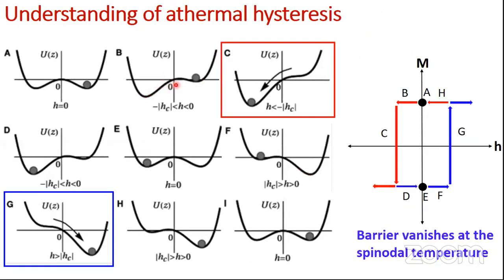So now, if we have some kind of fluctuation, sufficient that the system can cross this activation barrier, then the system will transform here, not here. But if the thermal fluctuation doesn't take part in the phase transition business, then the phase can persist right up to the spinodal point where this barrier completely vanishes and the phase will transform through rolling down a hill. So this kind of transition is called an athermal transition. Here the barrier is completely vanished, and you can see that the free energy itself is discontinuous, not the first order derivative of the free energy. That's why we are calling it the zeroth order, because the free energy itself is discontinuous at the transition point.